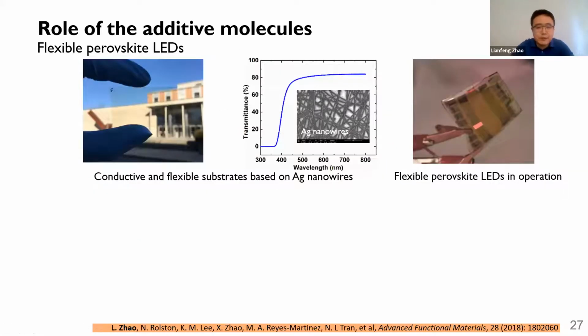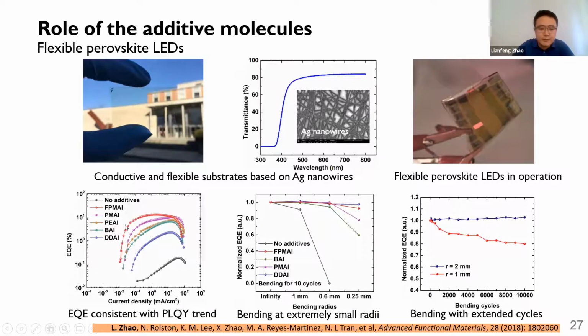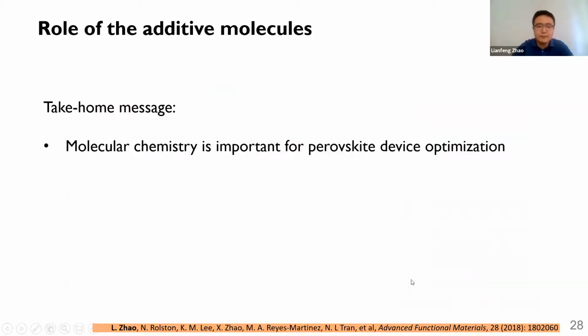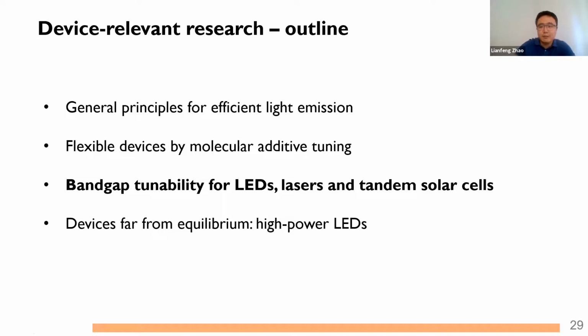Based on that, we demonstrated flexible perovskite LEDs based on silver nanowire electrodes. Consistent with our previous observation, the fluorinated additives give the highest light emitting efficiency and the best mechanical stability after conducting the bending test. So the take home message for this part is that molecular chemistry is important for the development of perovskite devices. Then I will show you our efforts towards the bandgap tunability and their applications in LEDs, lasers, and solar cells.